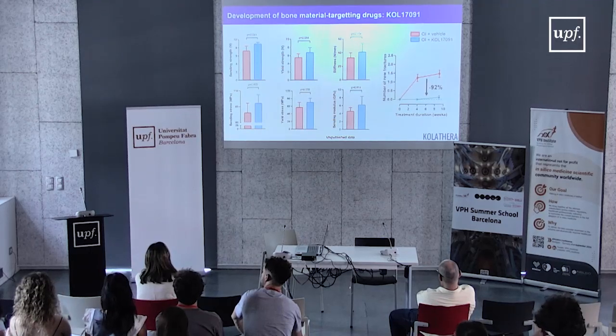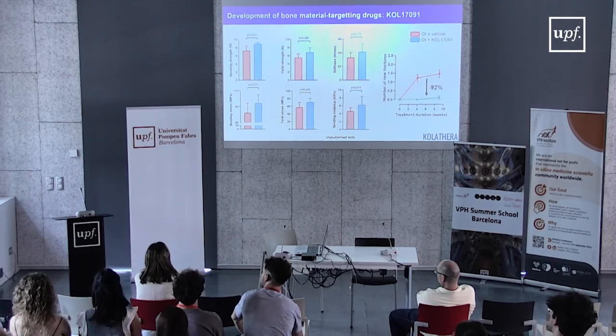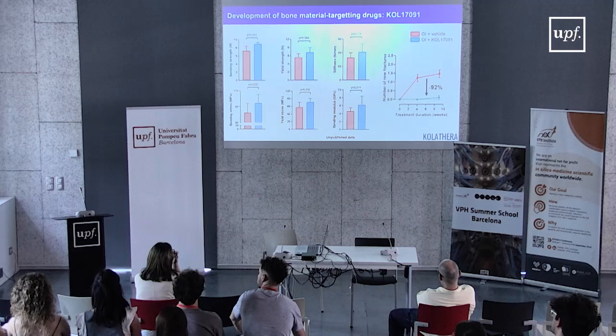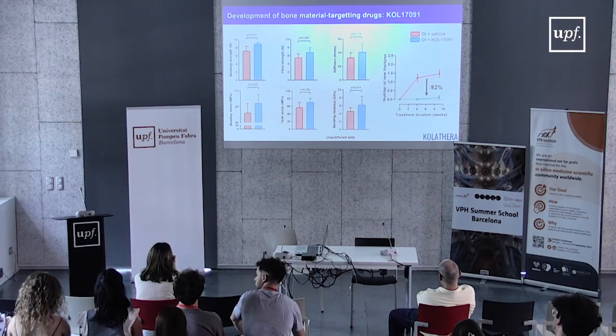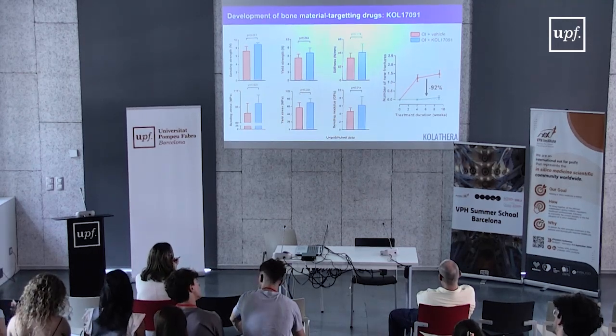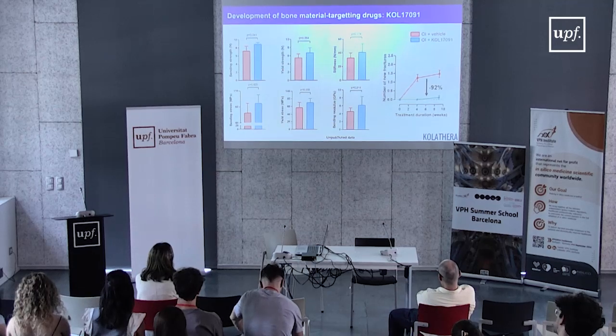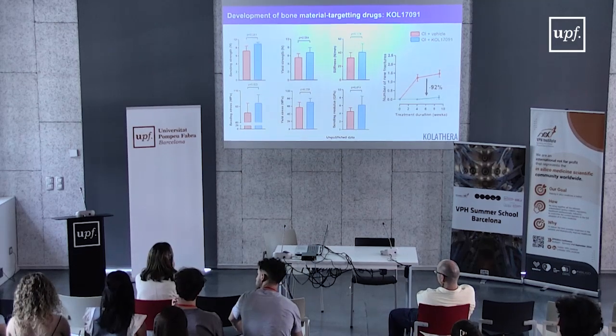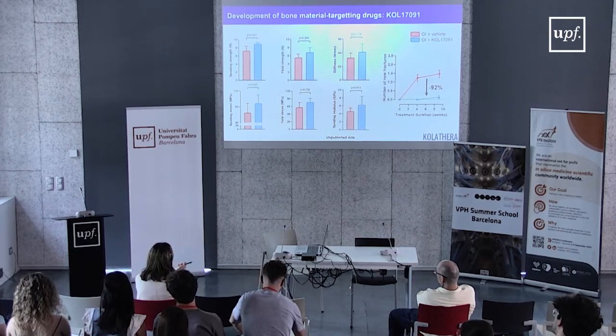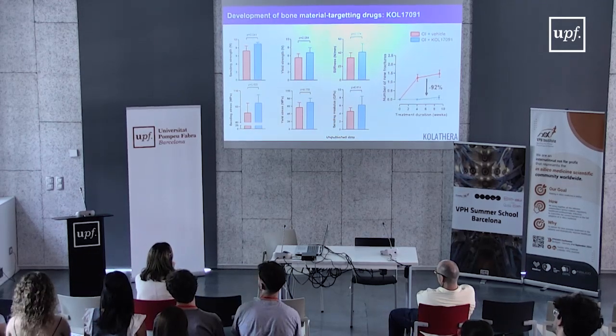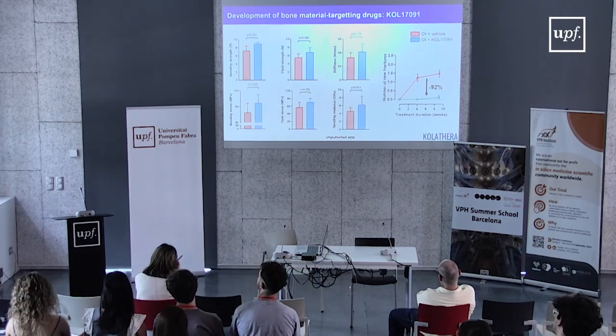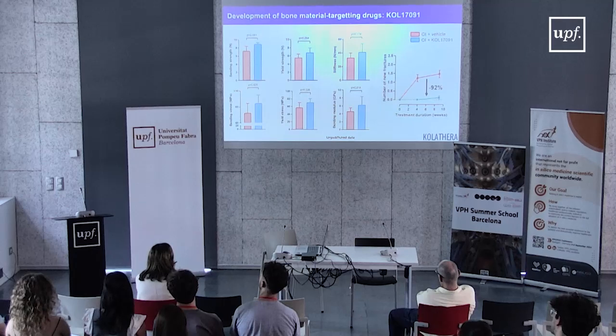Just to give you an idea, romosozumab, the newest anabolic treatment, which is currently being developed also for OI, is reducing fractures by 50%. So by addressing the quantity of bone material, we can reduce the occurrence of fracture by 50%. By addressing perturbation of the nature of the bone material properties, we can reduce fractures by almost 90%. So it's a much more effective therapy than addressing directly the quantity of bone.